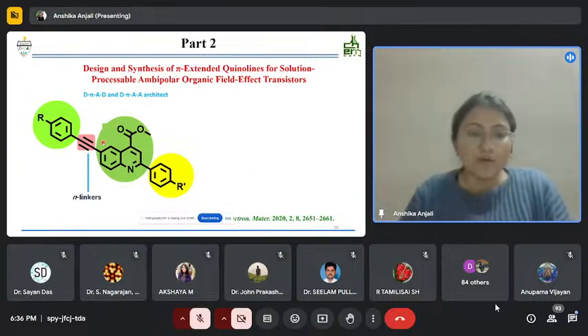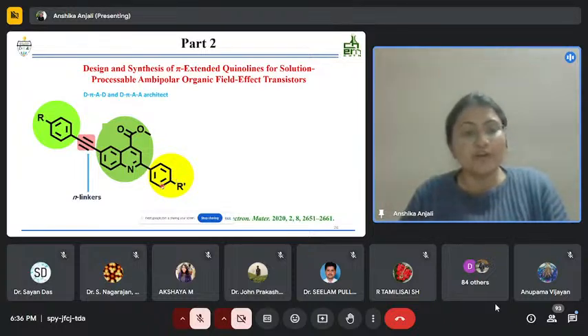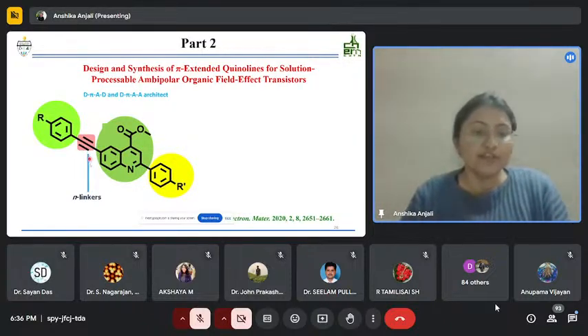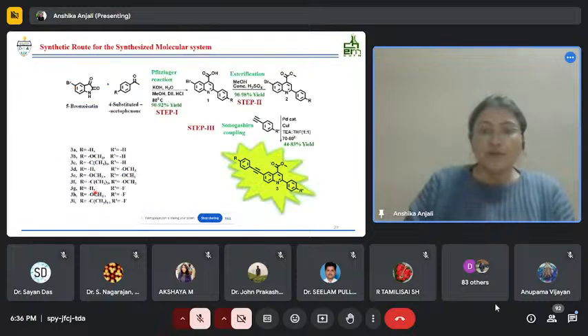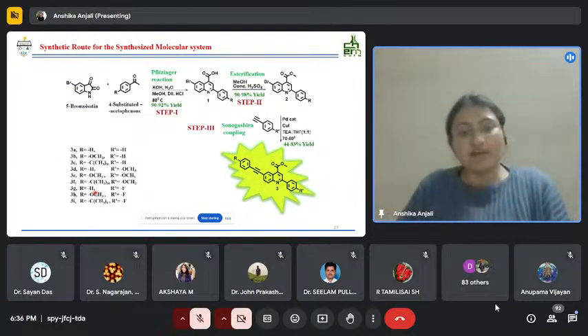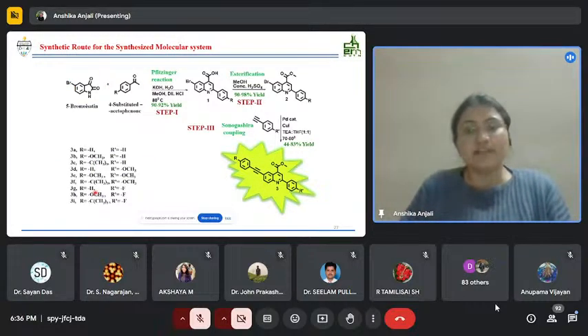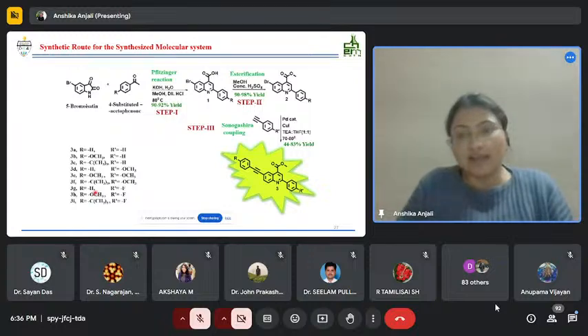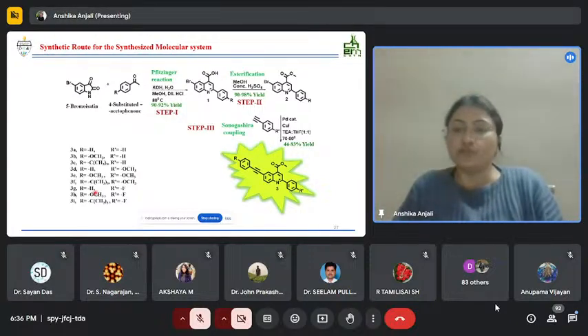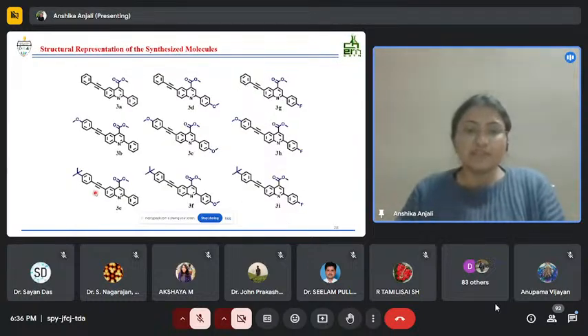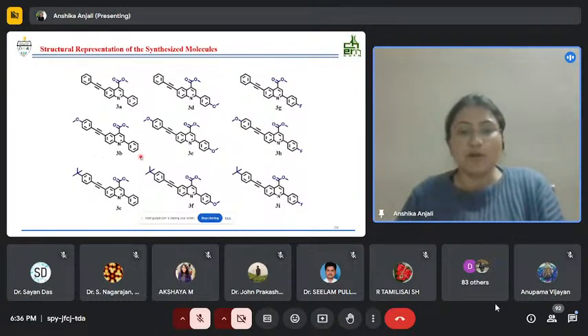Again we have taken 4-carboxylate as our core moiety. Then we are having a substituted phenyl group as our donor moieties, and here we have introduced acetylene as a pi linker. So again, for the synthesis of this compound, we have carried out the Pfitzinger reaction, followed by esterification, and the compound 2 then underwent Sonogashira coupling reaction to give the compound 3. So this is a structural representation of all the synthesized compounds.